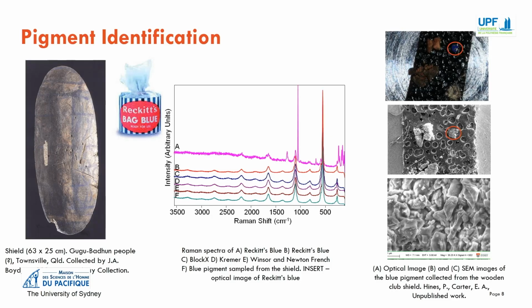The blue pigment was identified by Raman spectroscopy as ultramarine blue, but it was not determined whether it was synthetic, possibly Reckitt's blue, or natural ultramarine, lazurite, the main mineral component of lapis lazuli. Lapis lazuli is typically identified using either optical or scanning electron microscopy, since its morphology and particle size is distinct from the uniform, small, and rounded particles of the synthetic ultramarine blue pigment. We are re-examining the blue pigment together with other available samples to establish its origin.